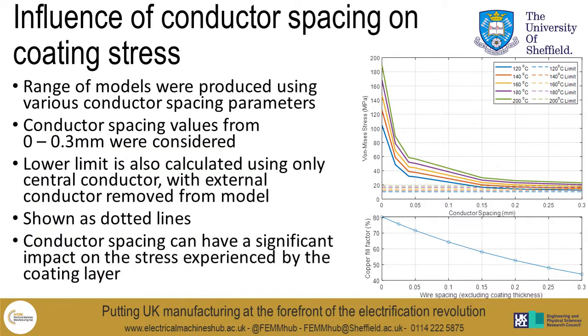So one of the parameters which is interesting to consider is the impact of conductor spacing on the coating stress. To do this, we produced a range of models with a variety of spacings from 0 to 0.3mm. The results of these at different temperatures can be seen on the graph on the right. We also calculated a lower limit for each temperature, which is denoted by the dotted line. This was calculated by only having a single conductor in the model with no adjacent conductors, and is the equivalent of the conductor in a very large amount of epoxy with no other conductors. What you can see from this is that conductor spacing can have a significant impact on the level of stress which is experienced by the coating layer and can't be ignored.